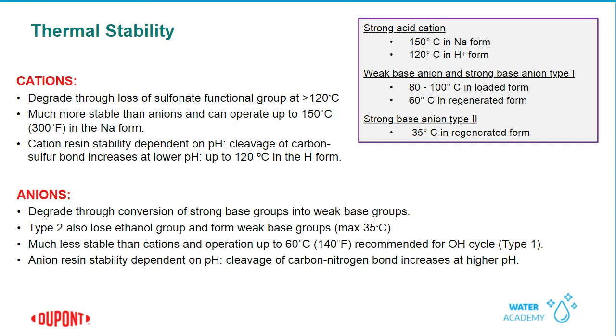And if you have a strong base type 2, or if you have an acrylic resin, it's even lower than that. We don't recommend going above 35 C in the regenerated form. Now, in the exhausted form, these resins can withstand higher temperatures, but if you're using them in demin applications where they will be in the regenerated form, like the hydrogen or the OH form, then you're going to have to be aware of these temperature limitations to get the most lifetime out of the resins.